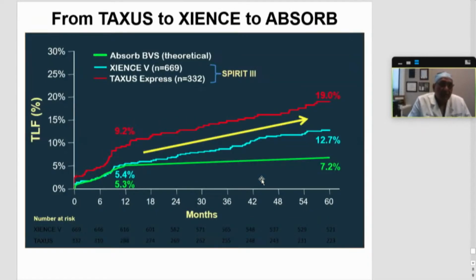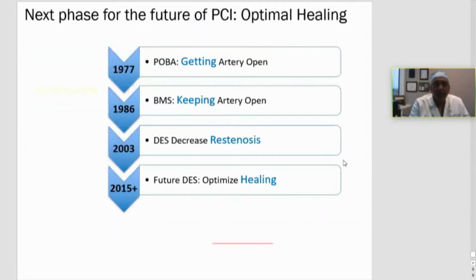So what we have is this challenge for us. We have this challenge where there is increased event rates at around 1.8% per year after the first 2 or 3 years, and it continues to persist. And that's why more often than not in trials which compare PCI versus CABG, we almost always lose out at 2 years onwards. So in the ideal world, if you can flatten this curve to this green line where you hardly have any perceptible event rates after the first year or 2, I think that is where the healing concept of drug-eluting stent should come in.